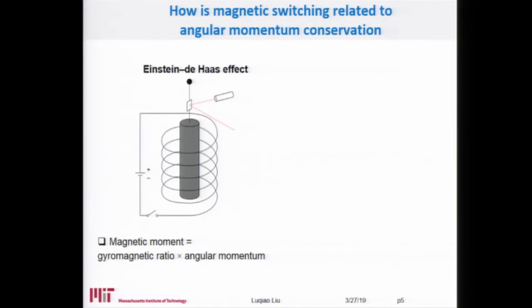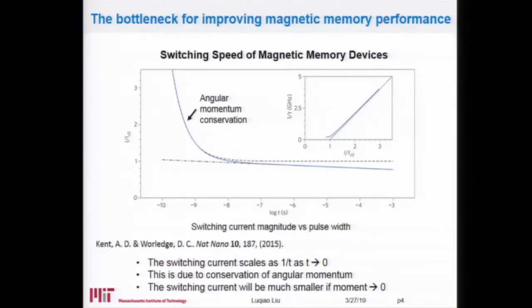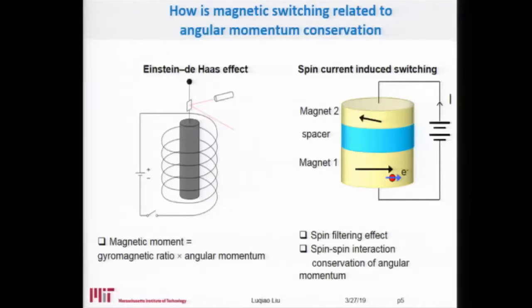So basically, given this, if we want to switch the magnetic moment, we have to satisfy the requirement of angular momentum conservation. And this spintronic device satisfies it this way. We have one layer of magnetic material which acts as the information storage layer, so its orientation can be pointing to the left or to the right. To switch its orientation, we apply a current across this tri-layer structure, which is known as a magnetic tunnel junction.